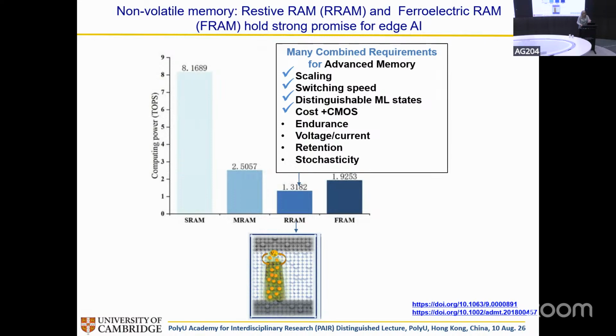So it's basically forming these defect channels. They're very random though, and that is a problem. The randomness, sometimes the size of them, and when you have a full filament going all the way through that's quite large, that can give you a very low resistance, and that means huge energy use. We don't want that. We want to be able to control those filaments, control these structures.